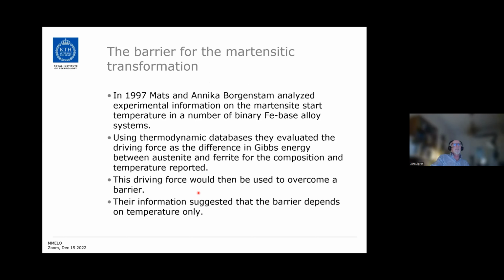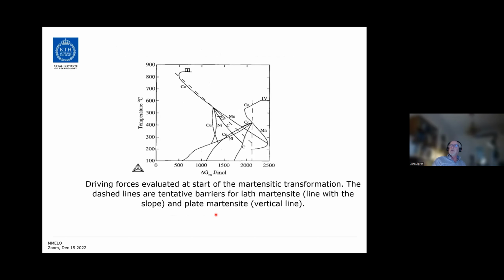And Mats, in 1997, and Annika Borgenstam analyzed experimental information on the martensite start temperature in a number of different binary iron-based alloy systems. And then they could use thermodynamic databases to evaluate the driving force as a difference in Gibbs energy between austenite and ferrite for the composition and temperature reported. And this driving force would then be used to overcome a barrier. And at that time, they concluded that this barrier only depends on temperature and not on alloy composition.